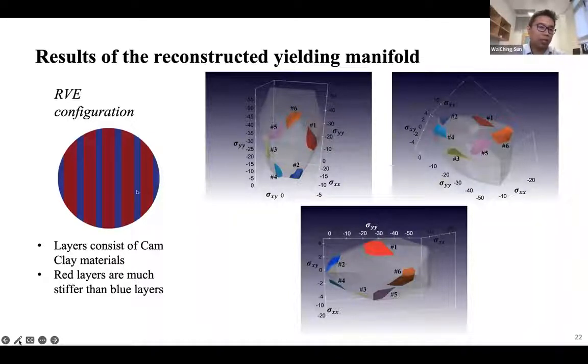And then we generate a database of these materials, loading them in different ways. We want to know what the exact yield surface is. And this is the six patches of this yield surface, in the stress space of sigma XX, sigma YY, and sigma XY. You can see that, surprisingly, the actual yield surface necessary to construct is way more complex than what we think, even though it's just a layered system.